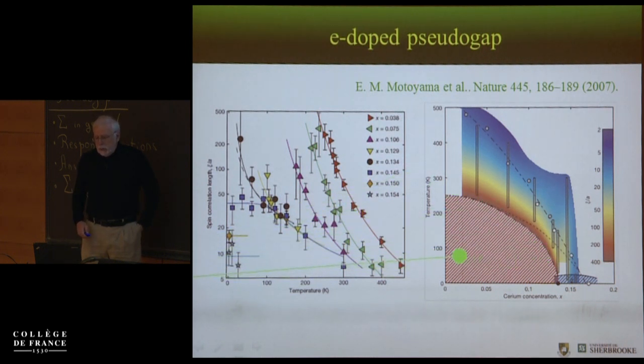This region here is where the antiferromagnetic correlation length becomes 400, so they decide that's ordered. And where the pseudogap opens up in the optical measurement is where these open dots are. Now you see in this region, you need a correlation length of 2 to have a pseudogap. But if you go down here in temperature, you need something at least 10 times bigger, if you follow the color code.